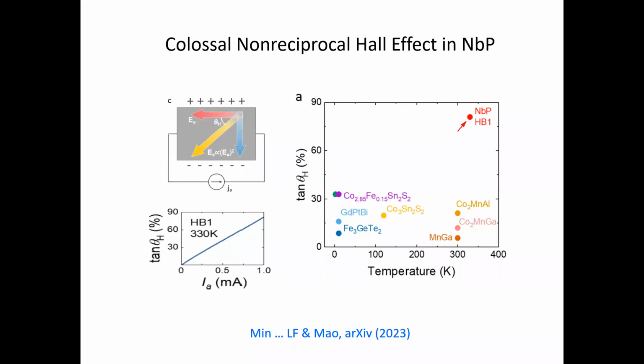In the linear response regime, this Hall angle is actually zero, because the material is non-magnetic. But because it's a nonlinear response, the Hall angle increases with the input current, okay? So this figure here shows the Hall angle for various materials. Niobium phosphide is here in this corner. At the input current of 1 milliamp, the Hall angle is already around 40 degrees and it works at room temperature. While these other dots show the linear response anomalous Hall effect, which is present in magnetic materials. And you can see that this niobium phosphide, despite being non-magnetic, is actually much larger.